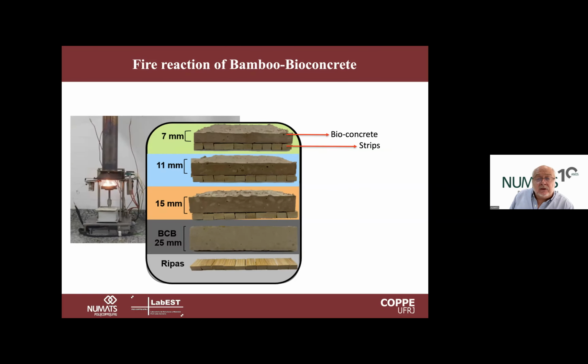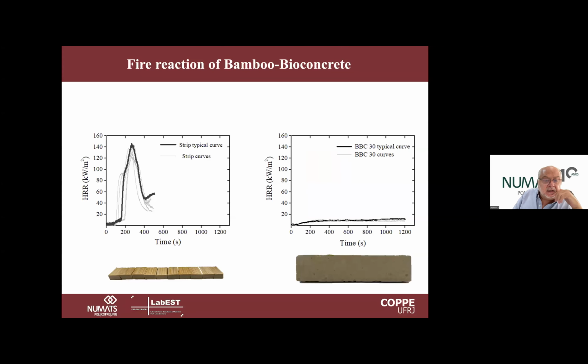The inorganic matrix already protects the biomass itself from the flux, even using up to 85% of biomass. The inorganic binding can protect against the flammability. So using these three lengths, 7, 11, and 15 millimeters, we did the test.